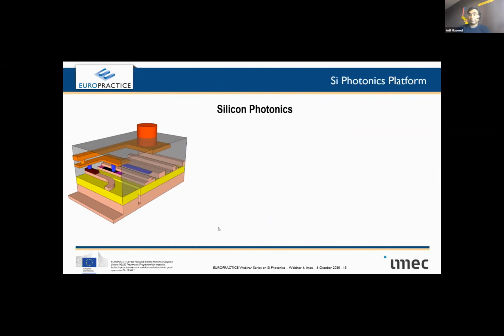Now to silicon photonics. This section will be shorter because a lot of advantages of CMOS technology we have already talked about. Now here again in another unlabeled cross section of silicon photonics, you can immediately see some differences from silicon nitride. To start with, this layer is actually silicon. So the processing starts on SOI wafers. It's a crystalline silicon substrate of around 700 micron thick, followed by a couple of micron of oxide, and then again a 220 nanometer thick silicon layer, which is patterned in a different way.